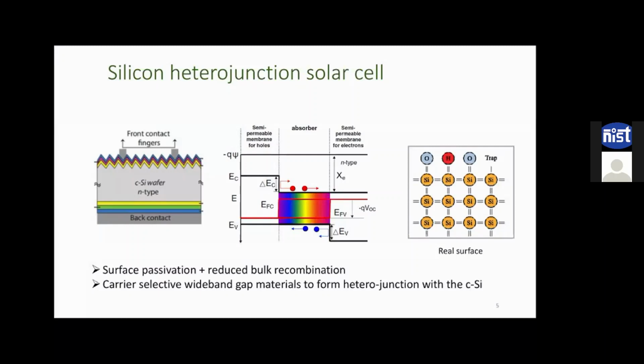I repeat: the ability of the heterojunction forming material to passivate the high density of defect states at the crystalline silicon surface, the ability to provide suitable band offsets for the proper transport of charge carriers across this hetero interface, and a high conductivity such that once the carriers are within the transport layer, they can travel smoothly towards the external load.